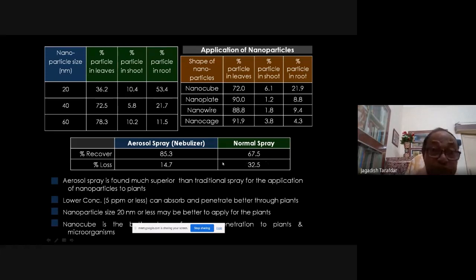So definitely, when you use nanoparticles, it is better to have as fine a nozzle as possible for spraying. Then the size matters a lot. We find that if your nanoparticle is 20 nanometers or less in size, then they penetrate better and are most effective. They are very effective. But if the size is more, I am showing you some results.